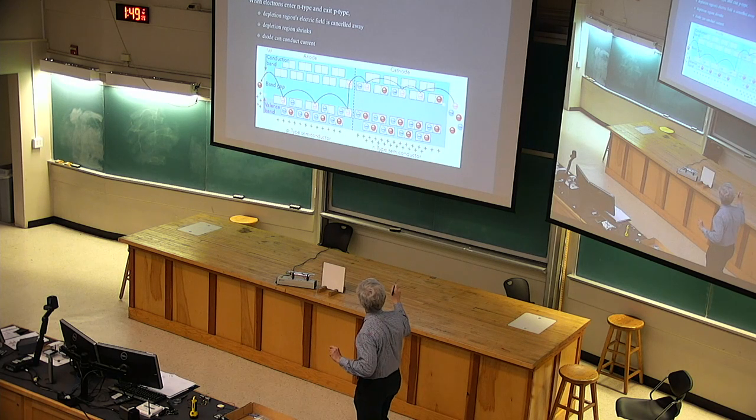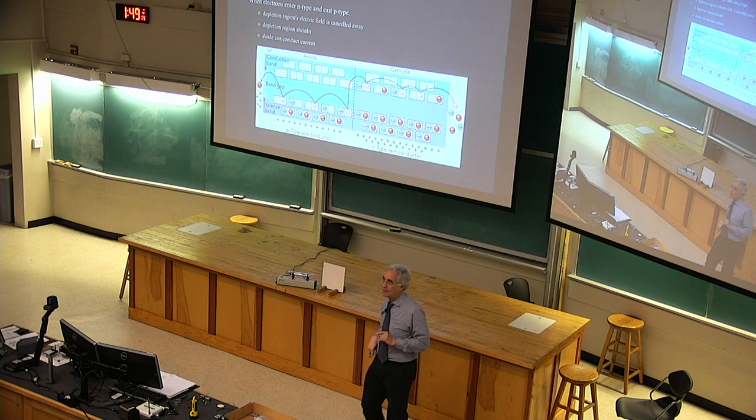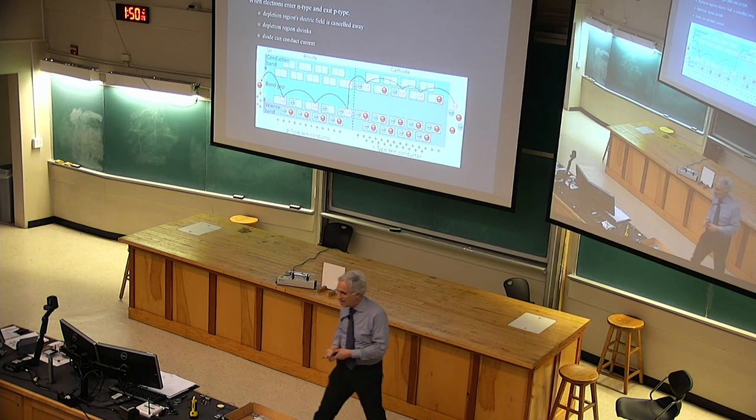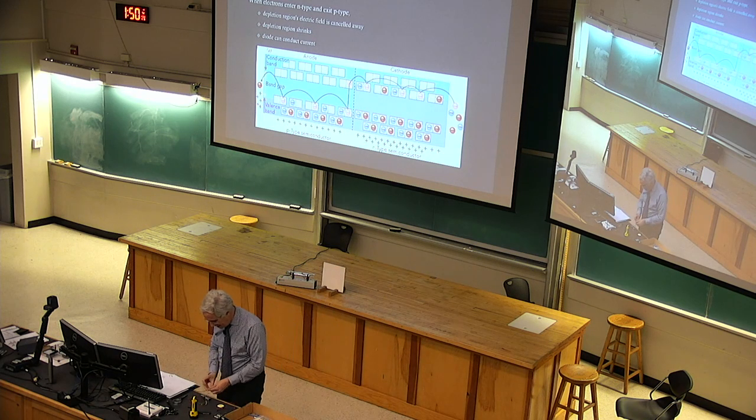You have to push the electrons in from the N-type semiconductor side and take them out of the P-type semiconductor side. That allows them to migrate across the junction again. You're undoing the electric field that built up that tried to stop them. And when they drop, they go in here. Once they get across the junction and make the step from up here to down here, there's a step in energy. They're shifting from one quantum wave to another. In a conventional diode, they create heat because their energy is released. In a light-emitting diode, the whole point of the story, they emit light.